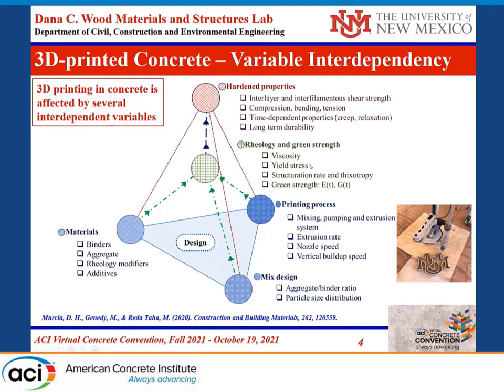Rheology is basically described by viscosity, yield strength, structuration rate, and thixotropy, and also represented by the green strength — described by stiffness evolution over time and mechanical properties including failure envelopes and shear strength. All of these together affect the final hardened properties: compression, bending, and tension capacity, but also critically the interlayer and interfilamentous shear strength between layers to ensure the 3D printing process does not affect the integrity of the concrete.